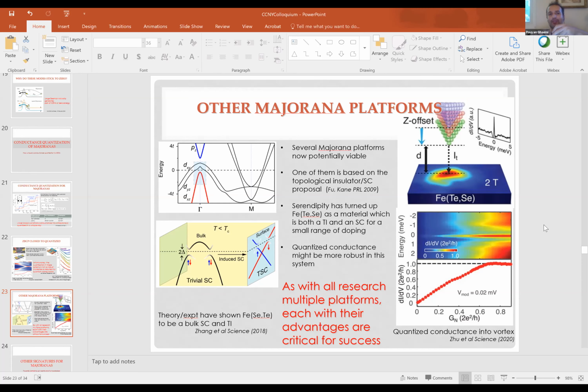Well, actually, in the picture we have, Jay, you change the type of superconductivity around the iron atoms. You make it more of a spin triplet. Yeah, you might get the triplet S equal to 1 superconductivity, which by itself could be interesting, right? But it's not going to be p-wave. Well, but even in that case, there will be a domain wall, and that will be gapless. But the point is, any gaplessness is very bad news for Majorana. So, okay, thanks. That's actually very, very helpful.